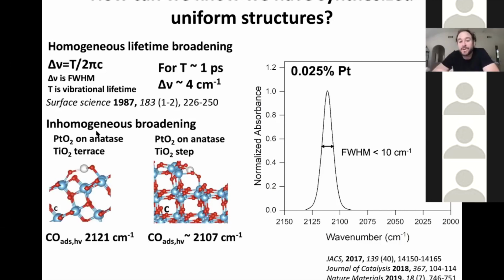The second way you can get broadening is inhomogeneous broadening. If you do a DFT calculation and you put a PtO2 structure on a terrace of anatase TiO2, you stick CO to it, and you calculate the vibrational frequency, you get about 2121. If instead you make that exact same platinum structure, still with the same coordination environment, but now at a step edge, and you stick CO, it's about 2107. So you can see here, this is already broadened. This would be broadened by about 15 inverse centimeters.